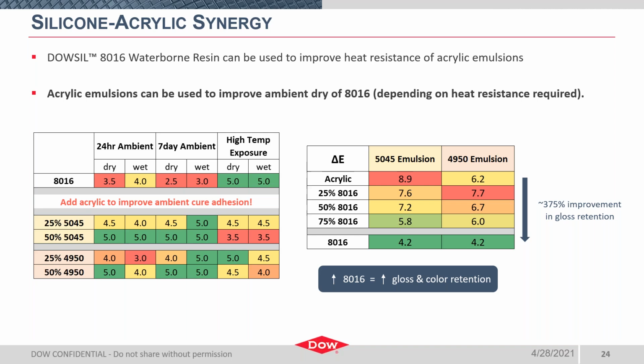And this might be required for handleability or moving coated metal parts before it would see a heat for bake cure and application. And here I'm referring to that top row in the left table. The post-heat adhesion is great, but we do have a need to improve that ambient cure adhesion. So we can look at modifying the 8016 versus modifying the acrylic like we examined before, or adding a small amount of acrylic to the silicone formulation to improve its ambient dry properties.